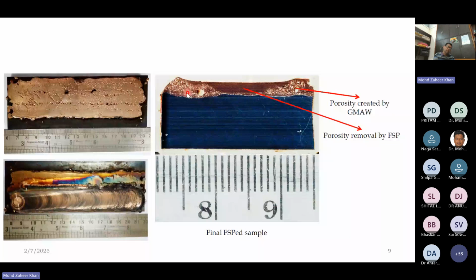So this was the first solution that we offered, that is, after a layer of a clad material is deposited on the substrate, we can always perform friction stir processing to remove the defects that have been created because of the deposition of the material by a conventional process.